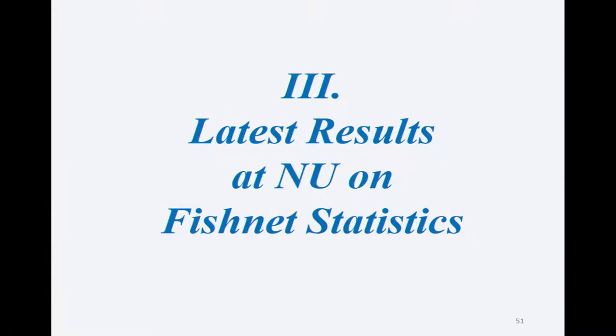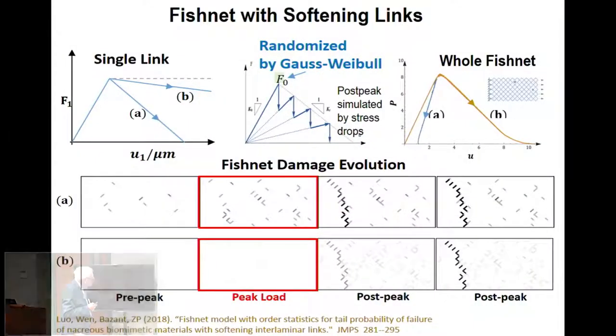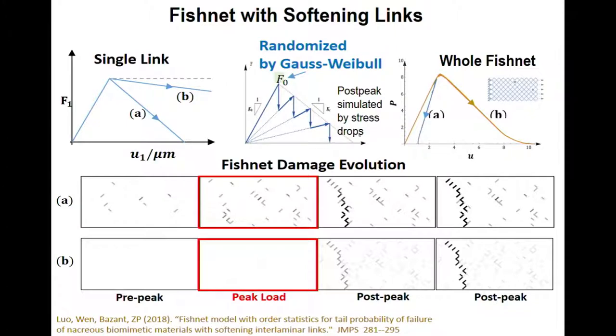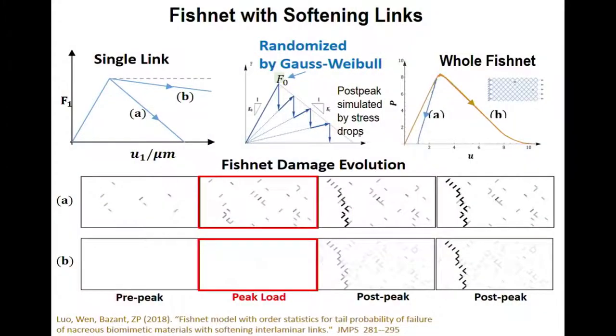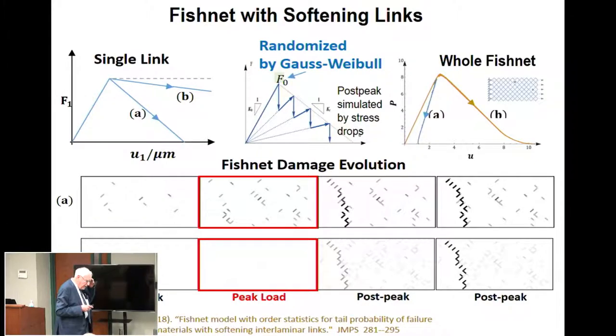Now some latest results over the last 4 months. Actually, a paper just appeared on this. Another question is, if we have this staggered platelet arrangement, I assume that the bond between these two fails as soon as the crack forms and it runs dynamically through the length of the connection between the two platelets, the biopolymer. But that's not clear. It may work in a cohesive way, where you propagate a long crack and then it becomes dynamic. And if there is a long crack, what it means in practical terms is that the transmission of force